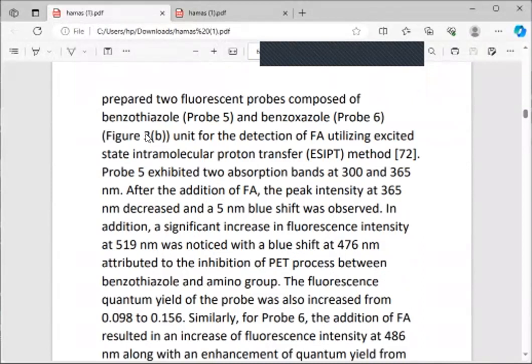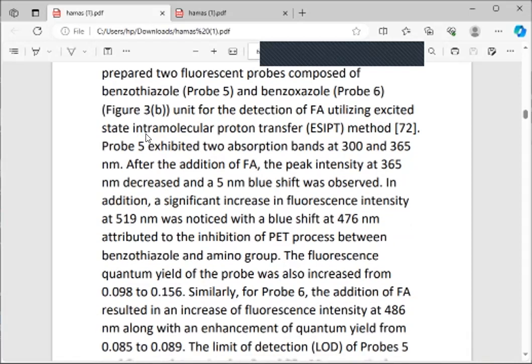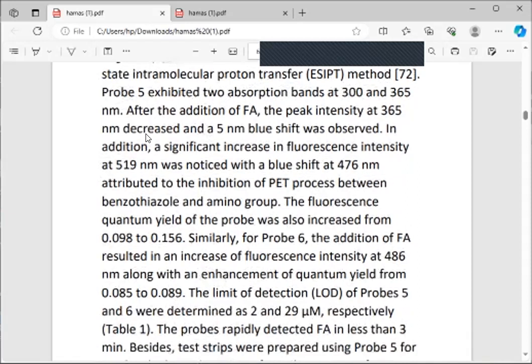of the PET effect. The probe shows high selectivity in the presence of several other organic compounds such as acetone, other aldehydes, formic acid and acetic acid. The detection limit of the probe was determined as 900 nM. The probe was able to successfully detect FA in several food samples. Nanofibers were fabricated by blending the probe with a polymer followed by electrospinning. Moreover, upon immersion of the nanofibers into water containing FA, the response was noticed. Another probe was also reported by Yuan and co-workers for the extremely selective and sensitive detection of FA.